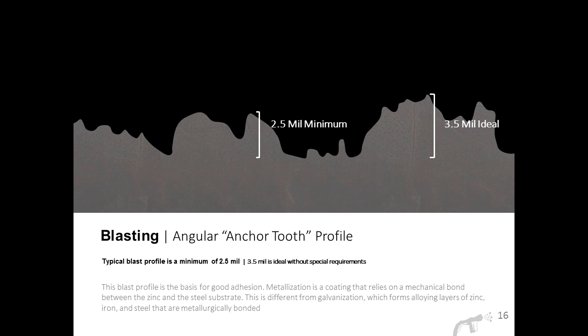So in order to get the proper adhesion for metallizing specifically, the steel really needs to take on what we call an angular, sharp anchor tooth profile. This is really the key to getting good performance out of a metallized surface. The reason why the angular profile is so important is metallizing is a coating that relies on a mechanical bond between zinc and the steel substrate. Ideally, we'd love to get about 3.5 mils of profile depth. 2.5 mils as a minimum is really the necessary requirement in order to get good adhesion.